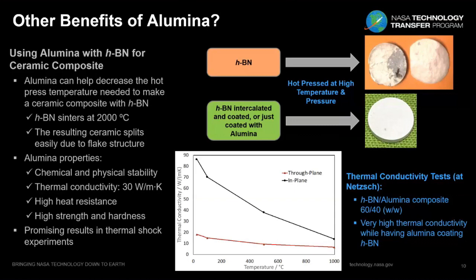So here I'm demonstrating a sample with 60% hexagonal boron nitride and 40% alumina, that we were able to make into a puck. It was tested and measured for thermal conductivity, and in-plane conduction is almost 90 watts per meter Kelvin at room temperature, and through-plane conduction is almost 20 watts per meter Kelvin. Those are very good values, and they decrease when they get all the way to 1000 degrees, but it is very impressive to see almost 20 watts per meter Kelvin of conduction through plane in this ceramic composite. I also have to say that we can make very strong pucks, even having 90% boron nitride and 10% alumina.